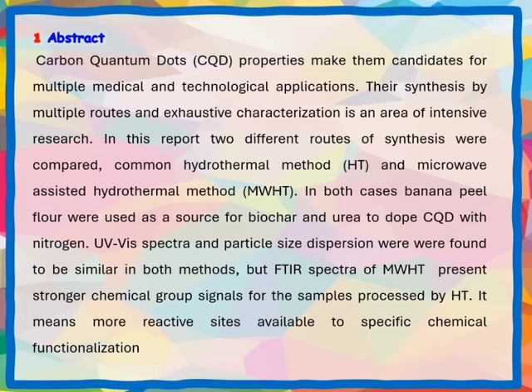with nitrogen. The ultraviolet visible absorption spectra of the synthesized carbon quantum dots are very similar for the two series of experiments, presenting an absorption band at 254 nanometers. The particle size measured by transmission electron microscopy was 9.9 nanometers in both cases. However, the Fourier transform infrared spectra shows clear differences. In the infrared spectra of the samples processed by the microwave-assisted hydrothermal method, more chemical groups found on the surface of the carbon quantum dots are identified.